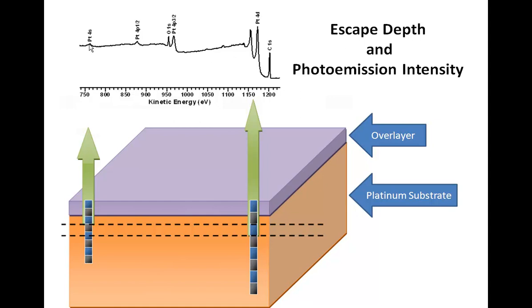If we have an electron of a given energy that is passed through the instrument and onto the detectors, then the probability that that electron is detected changes as a function of the kinetic energy. And we talk about the transmission function of an instrument that changes with energy, and that's because the lens, column, and the apertures all behave slightly differently at different kinetic energies.